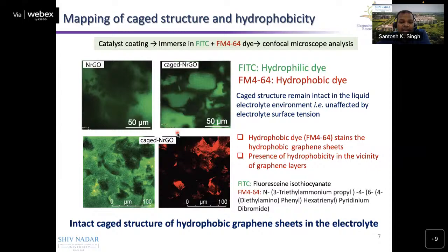And we tried to map out the hydrophilic and hydrophobic parts of this catalyst. We can see here that the hydrophobic FM464 is distributed over the hydrophobic part of the graphene, and the FITC, which is green, maps out the hydrophilic part of the catalyst. So by this technique, we can confirm the hydrophilicity and hydrophobicity distribution of these two catalysts.